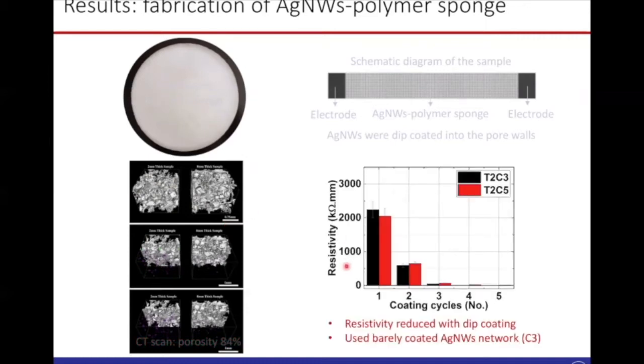Now we show the change in resistivity of the sample with respect to the coating cycle. As you can see, as you increase the number of coatings, the resistivity reduces and the sample becomes more and more conductive. And that's the classical approach, right? So we stop at the third coating here, where you have barely coated silver nanowire, meaning that the density of silver nanowire in this sample is very low compared to a highly conductive sample. So we believe this could be an ideal sample to prove our concept of welding.